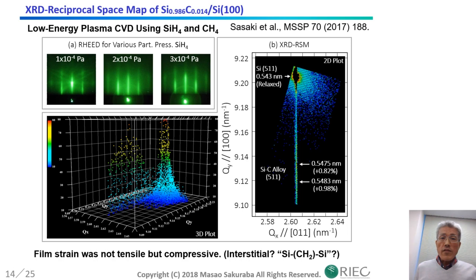The shape of the diffraction peak apparently indicates that the deposited film is lattice matching to the silicon substrate. However, film strain is not tensile but compressive, similar to the silicon-germanium alloy. This is an unexpected and strange result because the carbon atom is smaller than the silicon atom, so we need further investigation, but carbon incorporation at an interstitial site is considered at present.